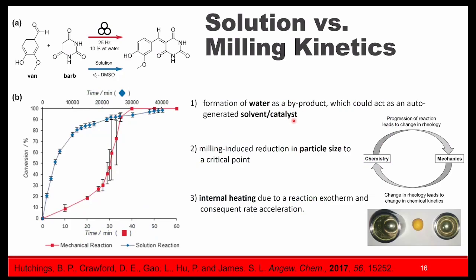And I think one thing that always comes to mind with mechanochemistry is, if you start to look at kinetics, how does this compare with processes in solution? This is another paper by Stuart James, where I think he did a really great job of looking at this Knoevenagel condensation reaction. And here's the plot. Here in blue, you have the solution kinetics, which is pretty standard exponential growth. But if you do the exact same reaction mechanochemically, excuse me, you get this sigmoidal shape.